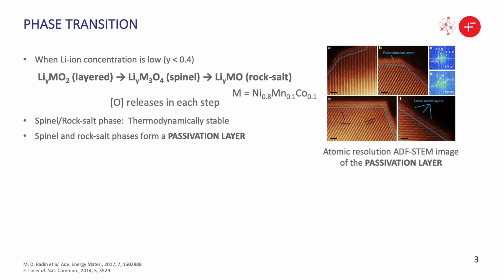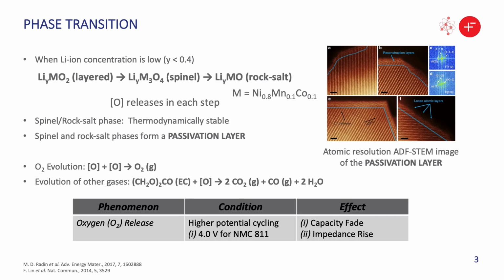Not only the power fade, but during the phase transition there is a release of nascent oxygen in each step of these phase transitions, and these nascent oxygens are much more reactive in nature. So they either produce oxygen gas just after diffusing out from the solid positive electrode phase, or react with the ethylene carbonate of the electrolyte to produce carbon dioxide and carbon monoxide. The gases produced, like oxygen, carbon dioxide, and carbon monoxide, are dangerous for the battery health. Experimentally, passivation layer formation and oxygen evolution have been observed whenever the NMC electrodes are cycled around 4 volts. This has an effect on both capacity fade and impedance rise.